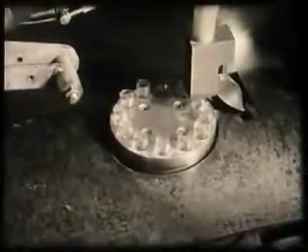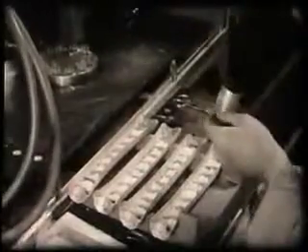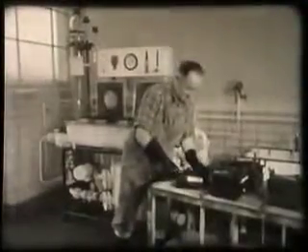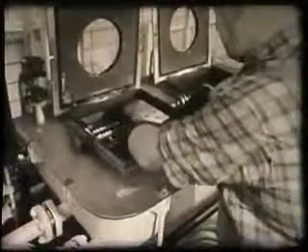You will remember that during the manufacture of the heater wire, the fine tungsten filament was wrapped around a molybdenum core, which served as a mandrel during the winding and as a support during the subsequent operations. As this core is no longer required, it is removed by immersing the heaters in a bath of strong acid, which dissolves out the molybdenum, leaving only the coated tungsten spiral.